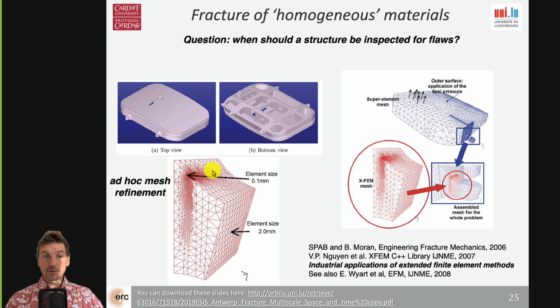So we assumed that during the whole propagation, there was no release of energy, that the stress being applied was the maximum stress that section of the component would actually see. We did not assume there would be a release of stresses due to the crack propagating. So my method, designed by myself and my supervisor Brian Moran, allowed us to look at much more realistic cases, which led us to different fatigue lives and allowed us to make very nice work forward in that area. And now these ideas are implemented in commercial codes, for example at Samtech in Belgium.